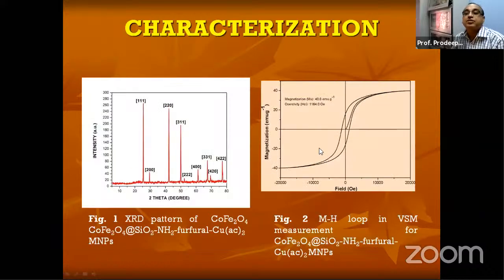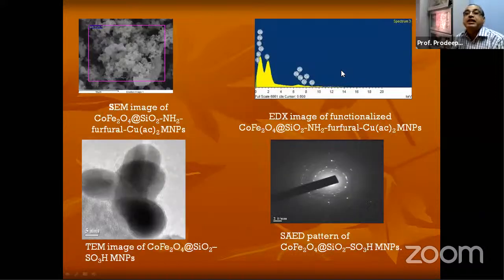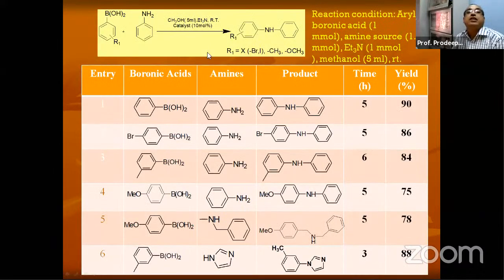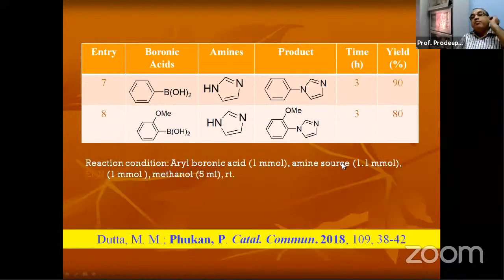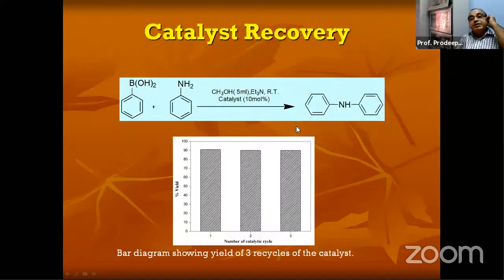So these are characterizations. I will not talk more about them. Of course, characterizations, SEM image, you can see TEM image, and these are the EDX spectra. And then finally, we did Chan-Lam reactions because it is a copper catalyst. So we have done several Chan-Lam reactions. And this is reusability. You can see here, it is very high. We could reuse up to 3 cycles, actually more than 3, of course, but we have done experiments up to 3 cycles.